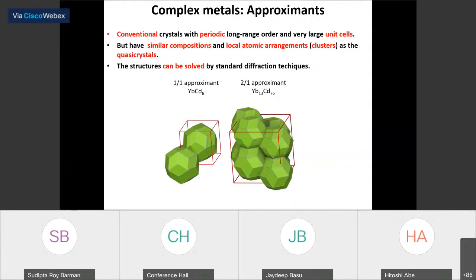So by complex metals here, we will discuss approximants. Approximants are basically conventional crystals with periodic order, long range periodic order, but they have very large unit cells. And they have local compositions and local atomic arrangements that are similar to the quasicrystals, and their structures can be solved by normal diffraction techniques.